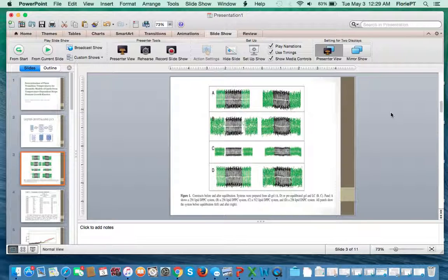The results from this study indicate Tm values that are higher and in closer agreement with experiment than those obtained through annealing studies. The use of a linear phase interface allows the measurement of the rate of the transition, yielding an estimated activation energy of 70 kJ per mole for the transition, with absolute rates of the same order of magnitude as those determined by experiment.